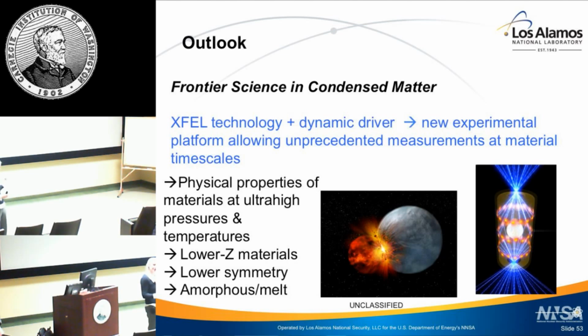So I'm casting these data in the context of, we see a trend, which might mean a transition to a higher coordination, maybe 6-fold. But these data alone, I cannot actually say coordination. I would love to be able to. So perhaps other techniques could be applied to the shock recovered material that I'm saying might have a different d-spacing for that diffuse peak.